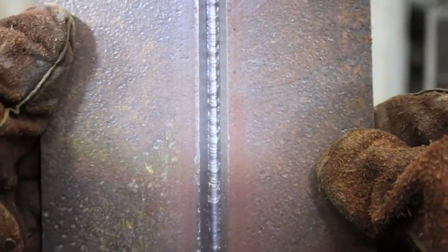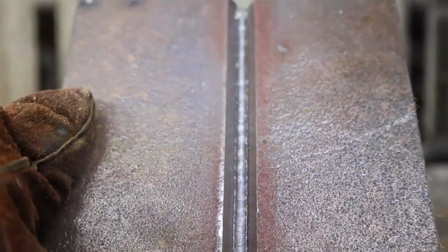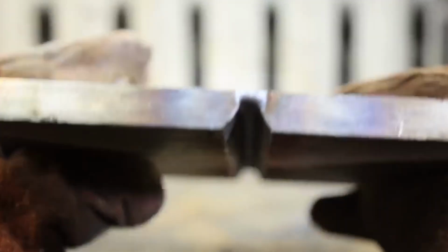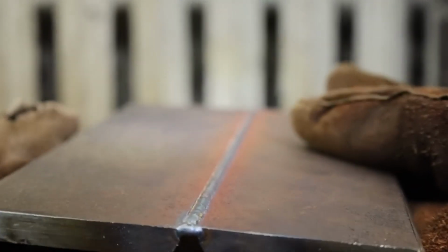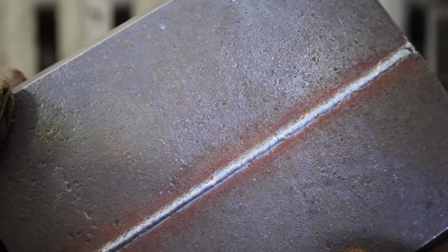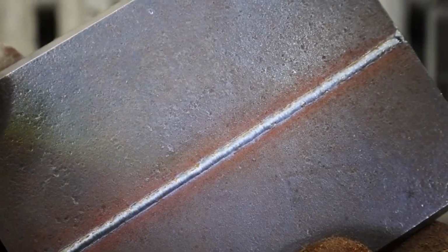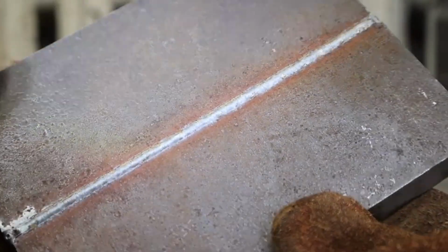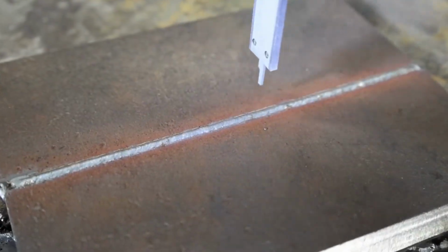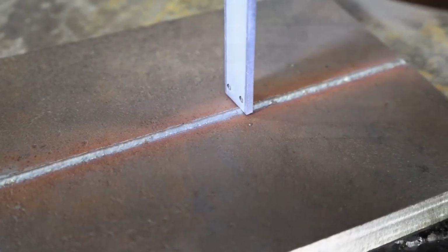Now our root weld is complete. As you can see, the weld bead is uniform in size and hasn't spread too far to the sides, it has primarily fused the root faces together. Let's now take a look at how the root weld appears from the backside. The root bead is consistent in size throughout the entire length of the weld. Its height is approximately 1.2 millimeters.